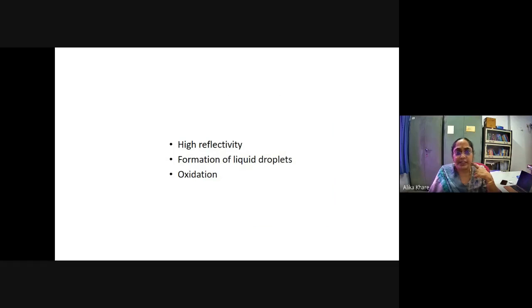There are several challenges also, though the technique is in principle very simple. Particularly the challenge we faced was the deposition of pure metal film - copper, silver, rhodium, etc. The problem with these materials is that they are highly reflective, around 90% or so, so hardly 10% of the radiation is absorbed by the substrate, and then the plasma is formed.